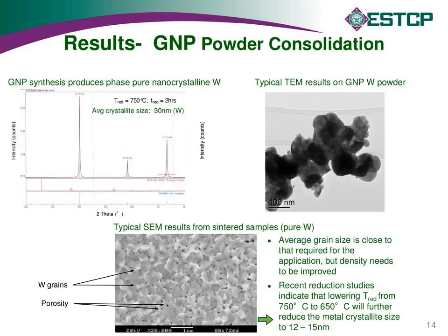All right. Next slide is number 14. The photograph in the upper right is an example of some of the powder being produced, and you see it's an agglomerated powder with very small individual crystallites of the tungsten in there, again with that about 30 nanometer grain size, and verified also with the XRD analysis.